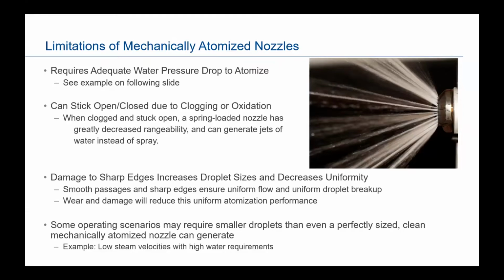But they rely on the water pressure to create the spray. Over time, these nozzles, depending on the material, you may get sticking due to oxidation or sticking due to clogging, a buildup of particulate. Typically they have relatively small passages that if strainers are not effective enough, you can get some plugging of them. This image on the right here is a spring-loaded nozzle that had been filled with just chunks of particulate. So instead of a nice cone of spray, you're getting a whole bunch of jets coming out of that nozzle because it's plugged up.